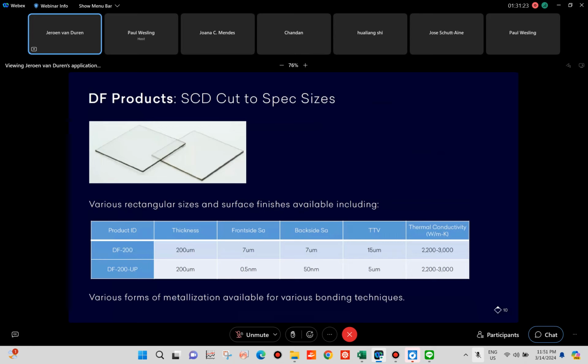So, our products available. We cut our diamonds to customer sizes, to specific sizes. There are various rectangular sizes and surface finishes available. Our standard product is the DF200. The DF200 has a thickness of 200 micrometers, so 0.2 millimeters, with a roughness on the front and the back of 7 microns. That's an Ra roughness of 7 microns, with a total thickness variation of less than 15 microns. And there we offer thermal conductivity of 2,200 watts per meter Kelvin and 3,000 watts per meter Kelvin.